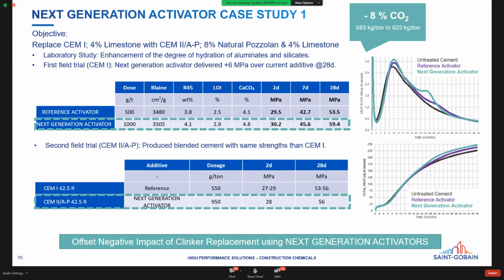So a second field trial was performed by producing the CEM2AP with the next generation activator at 950 ppm. The use of the next generation activator allowed to maintain the performance of the CEM1 treated with a conventional additive on the 2 and the 28-day strength. In this example, the additive has offset the negative impact of the clinker substitution on the cement performance. It allowed us to save 8% of CO2 thanks to the clinker factor reduction.